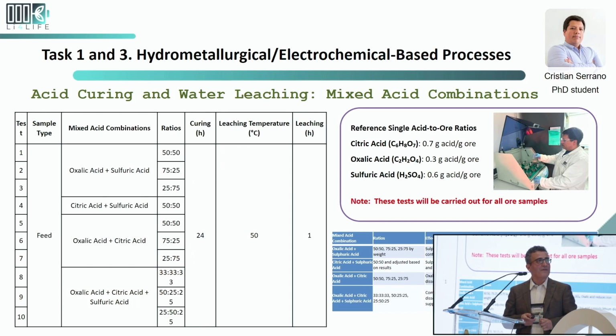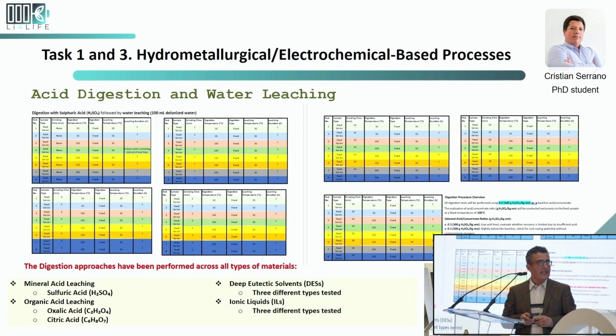And we also have our mixed acid, and we believe combining this acid also increases the efficiency, and we also look at the different acid concentration. These are mainly trying to have an alternative method for current lithium extraction. We also have the acid digestion, and we're using different temperatures and applying all our reagents.